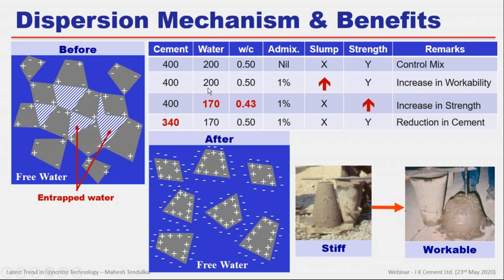So what we can do is reduce water and add the admixture. We have added 170 liters of water and 1% of admixture. When we reduce the water, what has happened to the water cement ratio? It is reduced. So slump is back to normal, but strength is increased. But why admixture is becoming very popular is the third point. Even if we don't want to increase the strength, we can reduce the water, reduce the cement, and maintain the same water cement ratio.